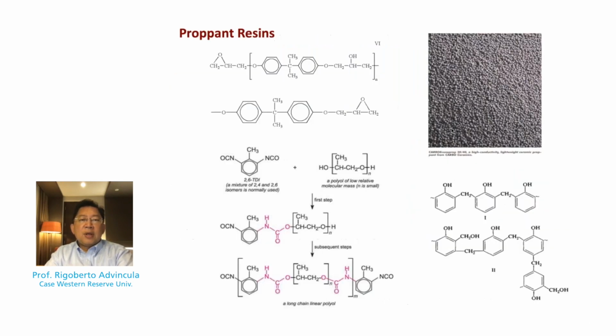real downhole conditions. Okay, so here I'm showing you several chemistry options for proppants. The most common one is based on a phenol formaldehyde resin chemistry, as shown. This is basically the reaction of a phenol and a formaldehyde, very old chemistry, in fact more than 150 years old. Bakelite comes to mind, and the word Novolac resin comes to mind. So these are basically cooked or mixed together with sand, and then finally coating it with a uniform thickness, possibly, and giving the sand a higher crush resistance.